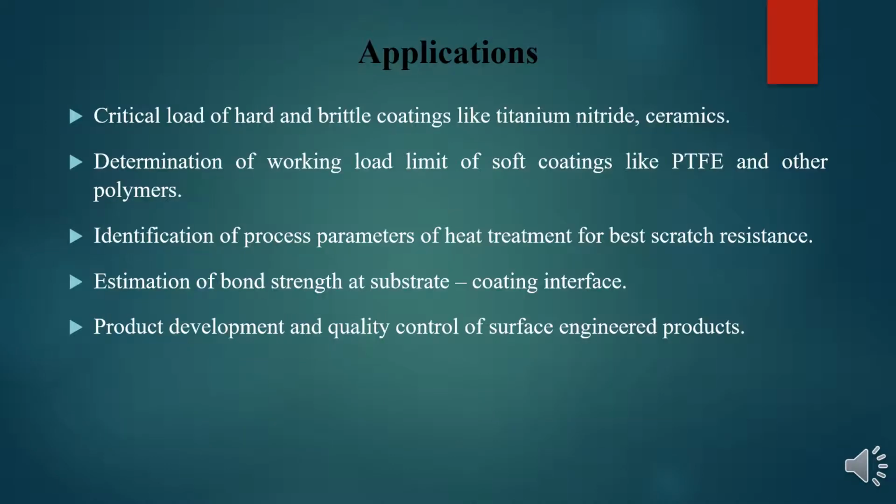The application areas of scratch testing are computing the critical load, meaning the adhesive strength of hard and brittle coatings like titanium nitride and ceramics. Also, determination of the working load limit of soft coatings like PTFE, polytetrafluoroethylene, and other polymers. Identification of process parameters of heat treatment for best scratch resistance, estimation of bond strength at the substrate coating interface, and also product development and quality control of surface engineered products.